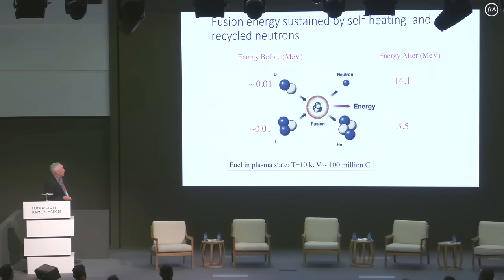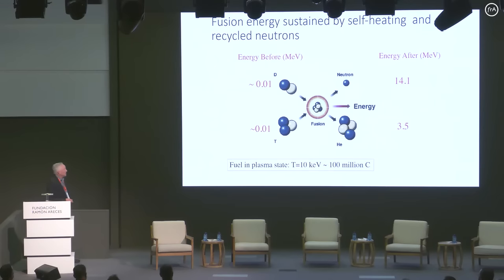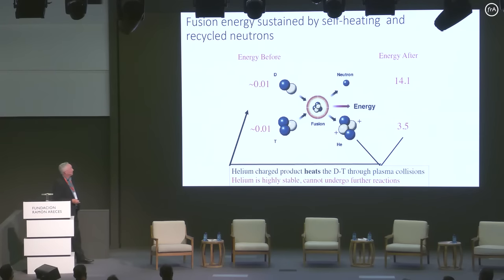But this also means that the fuel is in a so-called plasma state. It's the fourth state of matter, which stars and our sun are in. And that means that, even though it's only 0.01 MeV, it occurs at around 100 million degrees Celsius. Very interesting. So where is fusion energy? It's actually in the velocity of the particles, and they are very energetic when they come off. This helium particle that I'm showing you at 3.5 MeV, what does this mean? If I released this now, it would arrive in Boston in less than a second. That's how fast they're going. This is the amount of energy that's released, and this is why it's such a staggeringly good energy source.